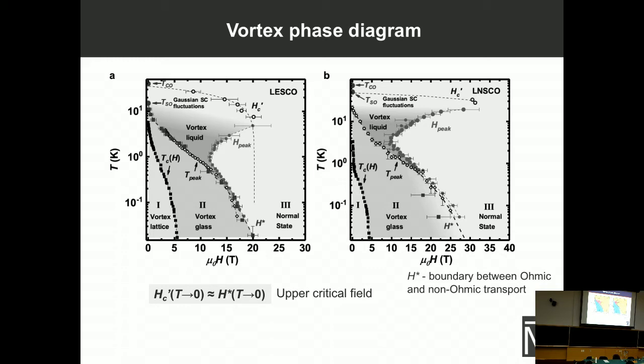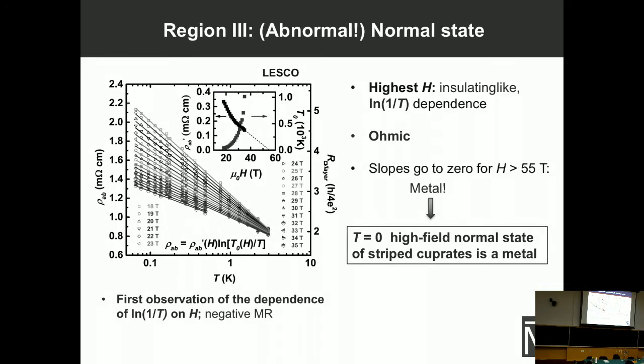So the normal state, this is what the temperature dependence looks like. This is a log scale. So it has an insulating-like temperature dependence, which is logarithmic dependence on temperature. So this has been seen before, like in early studies on underdoped LSCO. But what is new here and what is different is that here we see, as we keep increasing the field, this slope, this insulating-like behavior becomes weaker. And the black symbols here are these slopes which extrapolate to 0 at some high field for this material, above 55 Tesla. So this suggests that at even fields higher than this, the material will become a metal.